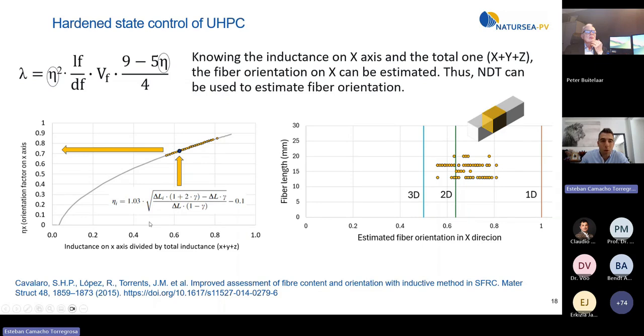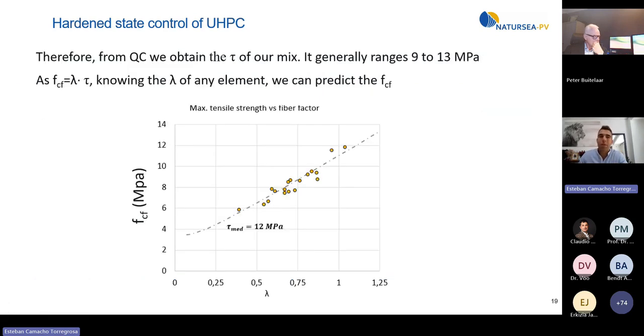We go to this equation, which is provided by the reference that you see below, and we can estimate the fiber orientation. After doing this with our device in less than 30 seconds, we can plot the result for different samples tested, and you can see that the fiber orientation is between 0.55 and 0.8, which is logical because our element is between 2 and 1 dimensions. It's something that makes sense.